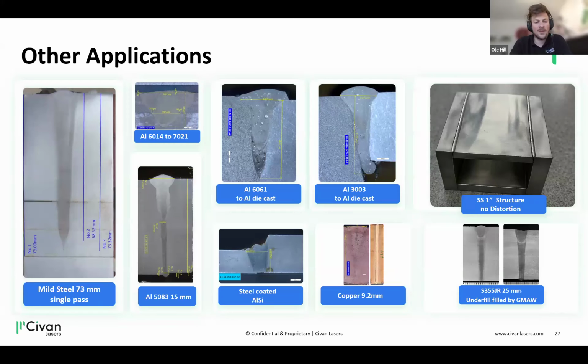Just a short overview of other applications that we have. We're not limited to just aluminum die cast and aluminum and copper. It's also applications of very, very deep penetration with our lasers that have up to 120 kilowatts of optical power. There you can see an experiment done to go in a single pass over 70 millimeter in a butt weld configuration. And also thick aluminum welding. On the bottom left, you see 15 millimeters of aluminum welded. And some of the other examples that I showed you as well of die cast to different kinds of alloys.